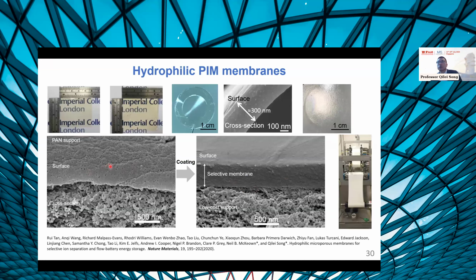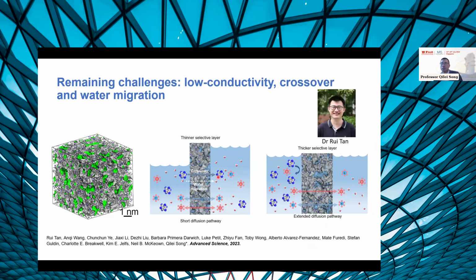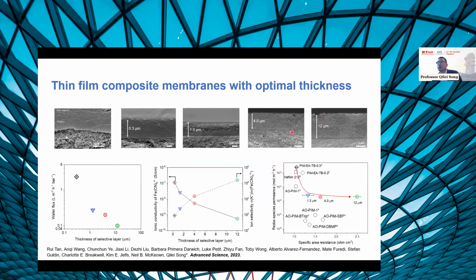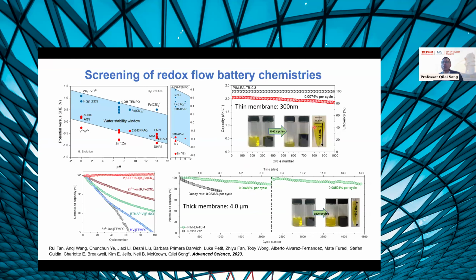But the challenge is that because these thin film composite membranes are hydrophilic, the water transport is quite significant. Because these polymers are solution processable, we were able to tune the thickness of these membranes from sub-micron to several microns. By enhancing the thickness of the thin film composite membrane, we can mitigate the water transport and also enhance the selectivity. But this is not enough because the polymer itself was not conductive enough, so we did not get great battery performance.